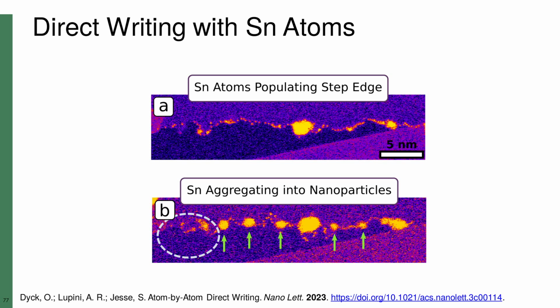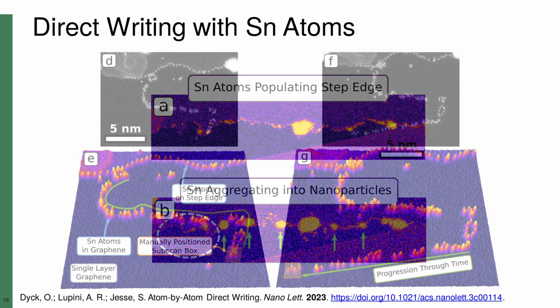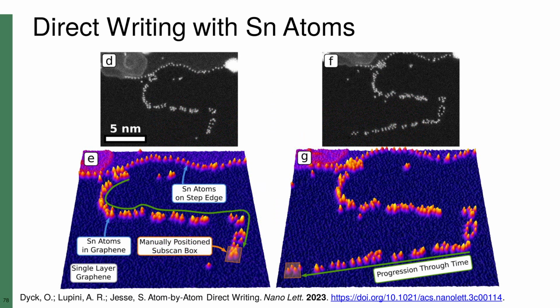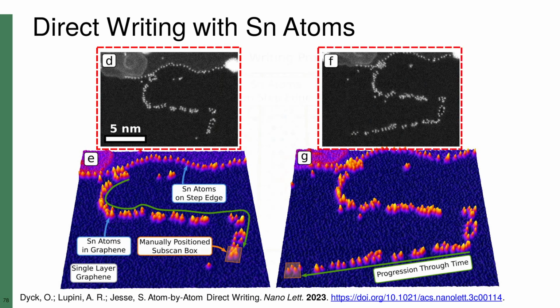Next, we are going to zoom into the circled region here. We can now more clearly see the tin atoms along the step edge, and of course, there is this curious line of atoms extending out from the step edge. What I did was create a small subscan box and position it at the step edge, so only that area was being irradiated. Then I manually moved the box across the graphene to write a line of tin atoms. I paused to take this image and then continued writing a bit more.